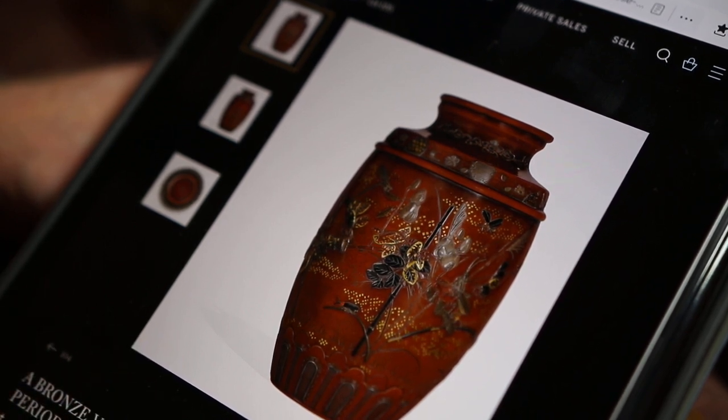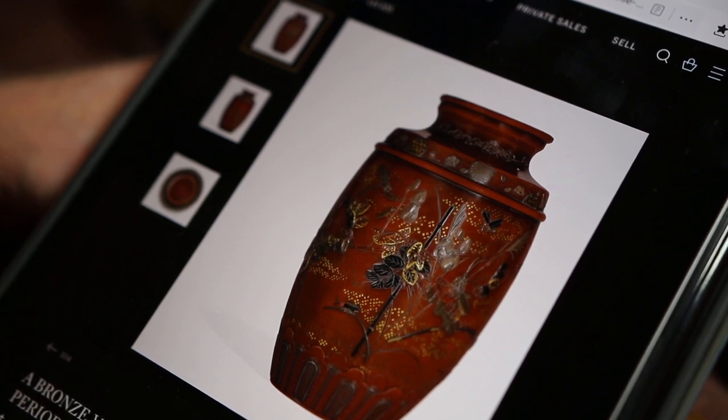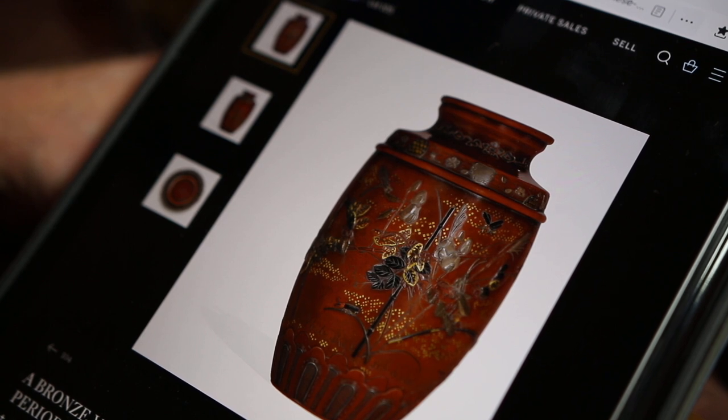That matte finish often happens in my experience where perhaps some zinc or tin in the bronze composition has oxidized excessively, and when it was cleaned, that's then removed. And so the patina is now altered because certain components which affect how the light is reflected off the surface are gone. The tonal qualities of the light, in terms of colour, alters.